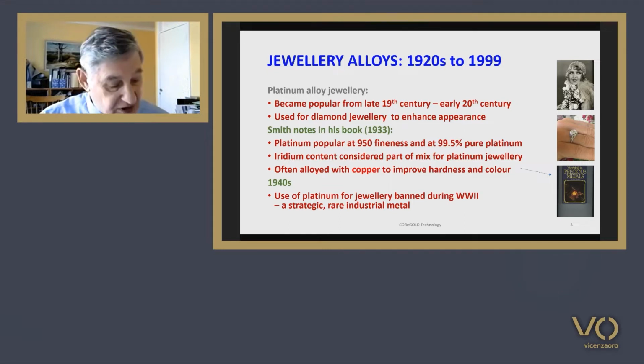Although some growth in demand began earlier in Japan in the 1960s for historical reasons linked to the ban on the import of gold until 1973. Platinum Guild International was formed in 1975 to promote the use of platinum in jewellery. This marketing and growth led to some alloy development, such as the platinum cobalt alloy for investment casting, and the use of gallium additions to produce heat-treatable alloys with higher strength and hardness.